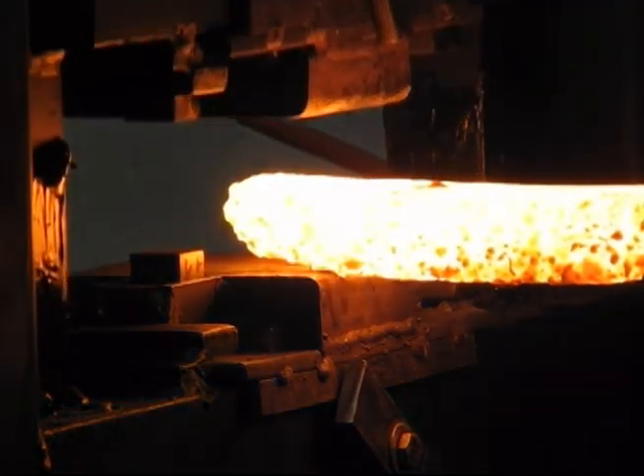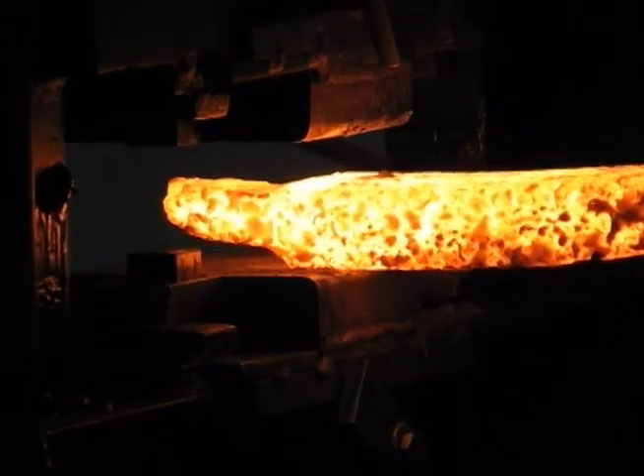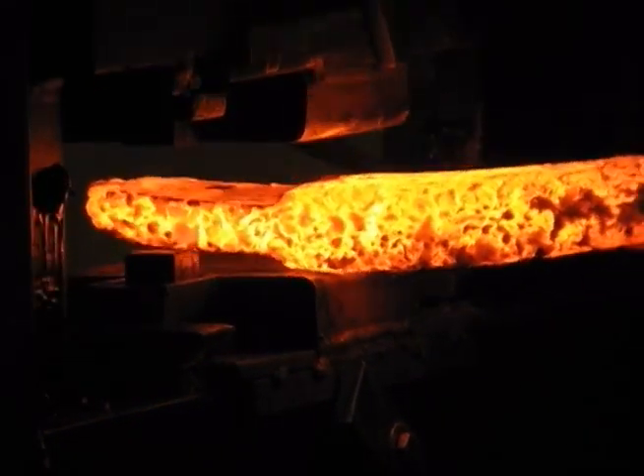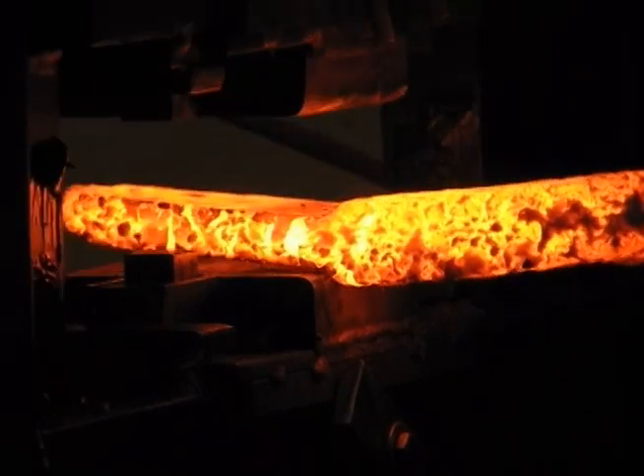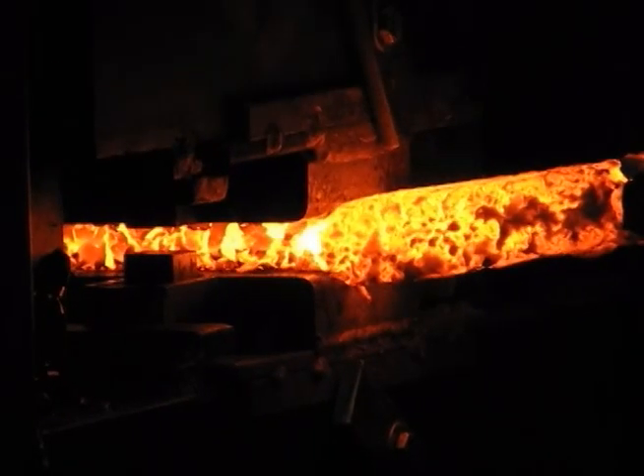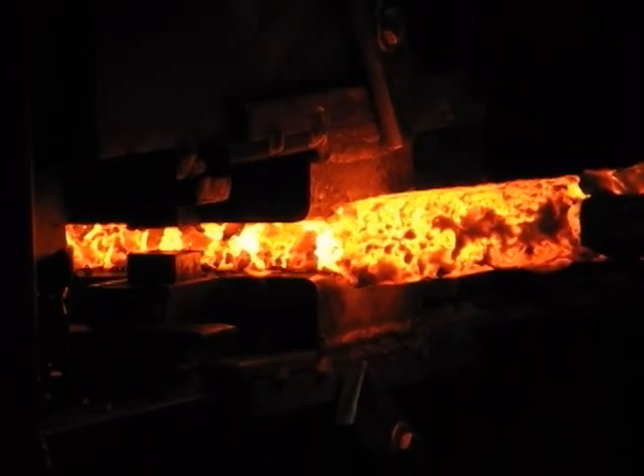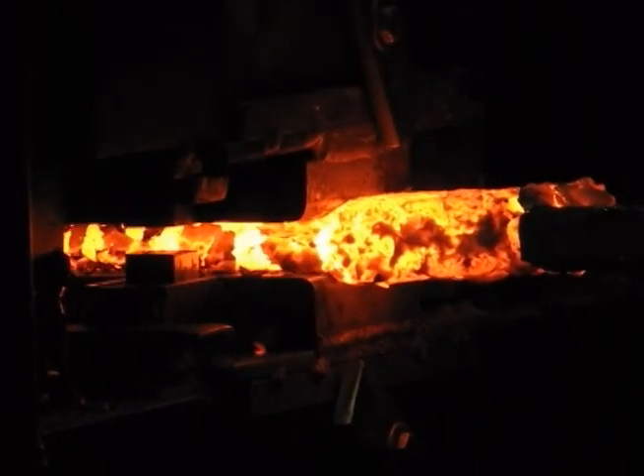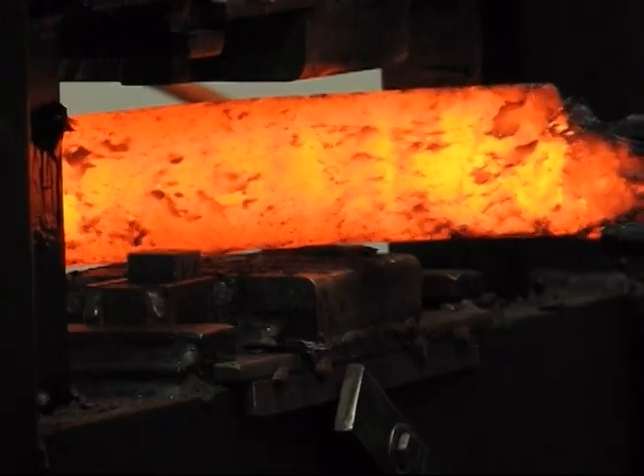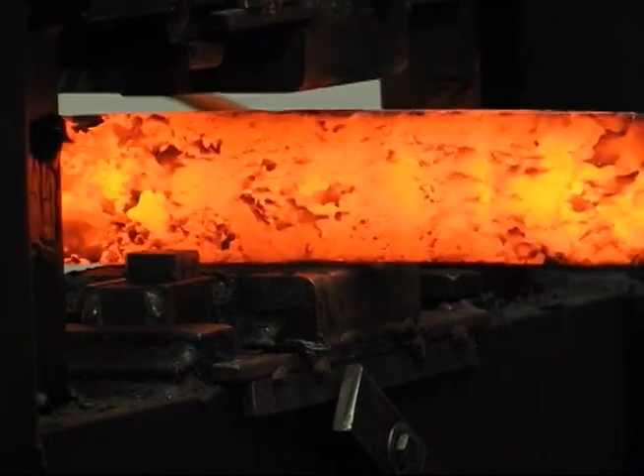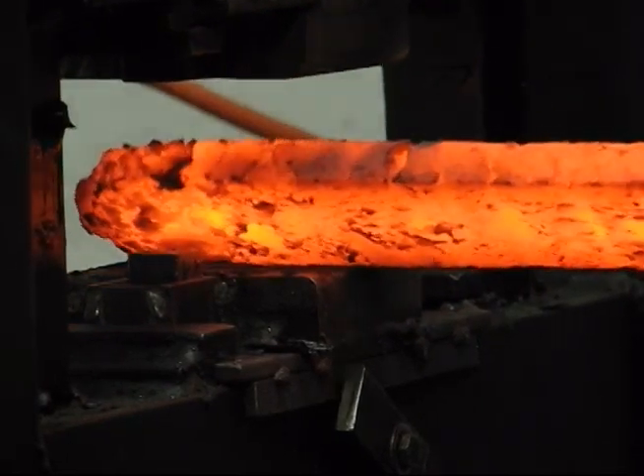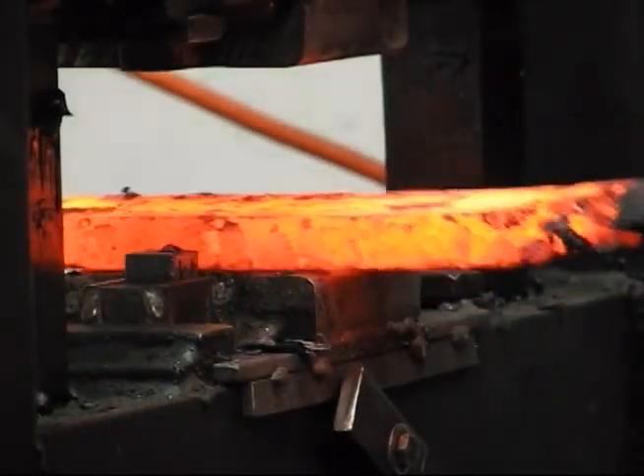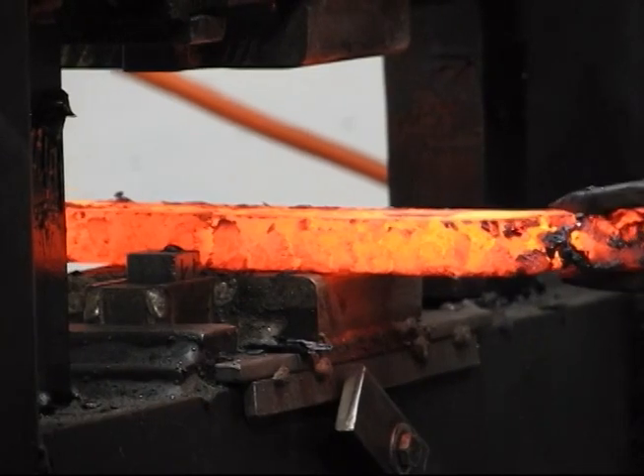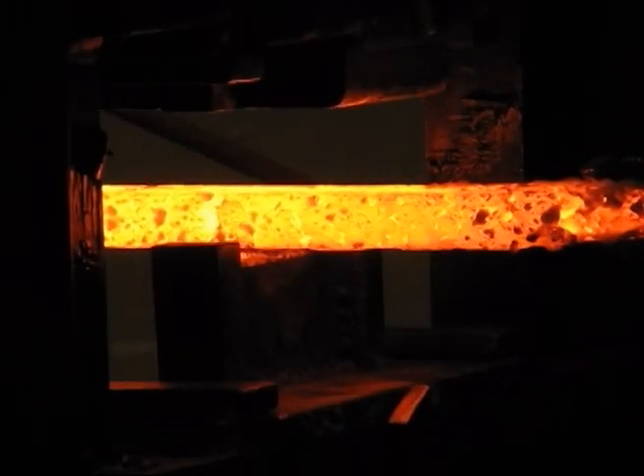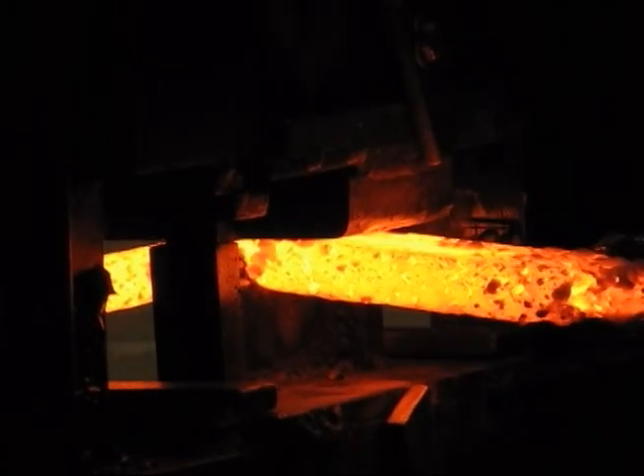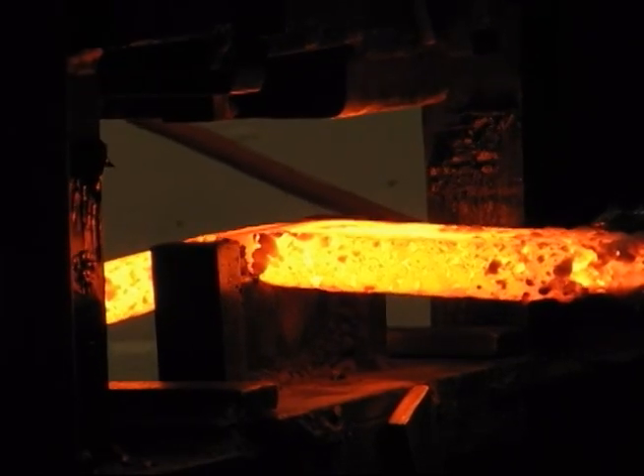The bar is further reduced in size to about 1/2 inch thick by 2 inches wide. The reason for these measures is no other than to comfortably fit the size of the jaws on this press. When the bar has reached the desired measurements, it's time to cut it in half. Jesus prefers not to cut all the way through and leaves enough material to work like a hinge and facilitate folding the bar later.